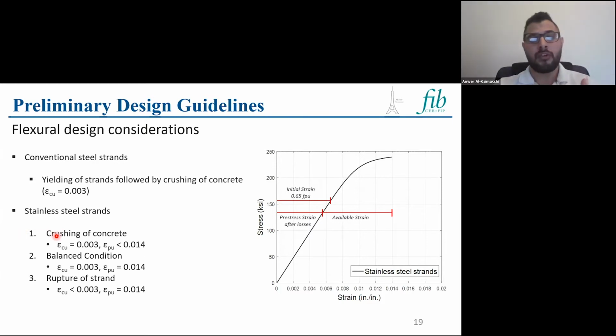The first one is to choose your member to fail due to crushing of concrete, where the strain in your top extreme compression fiber reaches 0.003 before the strain in the bottom layer of strands reaches the ultimate value of 0.014. Or you can have the balanced condition where both the strain in the extreme compression fiber and the bottom layer of strands reach their ultimate values simultaneously, and both of them fail at the same time. It's theoretically possible, but experimentally it's very hard because of the variance in the material properties.